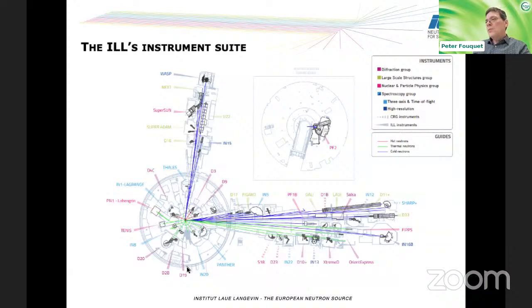Now, the whole setup at ILL is shown here. We have on the bottom left corner the reactor building. There are quite a few instruments already in the building of the reactor. And then there are neutron guides, which are mirror assemblies, basically, which guide the neutrons out to instruments that can be up to about 100 meters away from the reactor core. And they are all in two large guide halls. And that's where you would find the instruments when you do experiments at ILL.